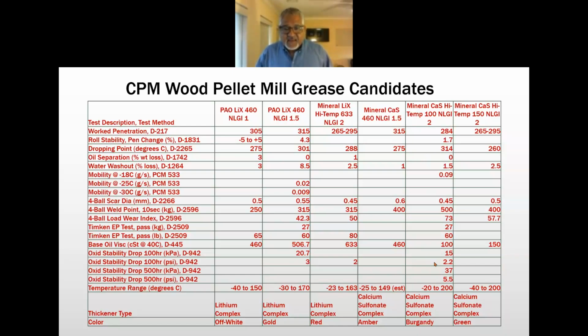Remember I said this is a high load environment, so you want to look at wear protection data when you compare the recommended lithium complex grease and the calcium sulfonate grease. The recommended lithium complex grease types had a 4-ball weld point up to 315. The 4-ball weld point for calcium sulfonate greases was 400 and 500 kilograms. Our load wear indexes showed a disparity also. The CPM recommended type greases had load wear indexes of 42 and 50. We got a 73 load wear index and almost 58 for the calcium sulfonate grease.